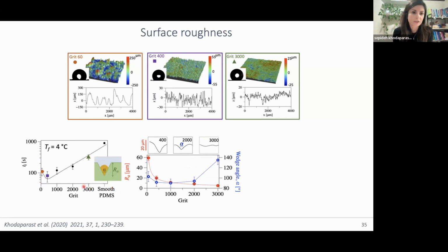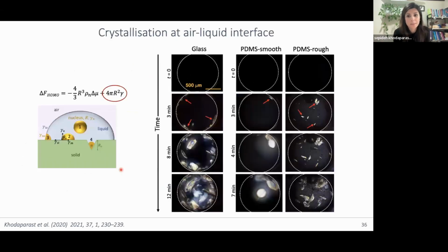you see that there's a minimum value in the curve, and it's not monotonic. It is clearer when you look at both the surface roughness and the wedge angle. The surface roughness goes down with the grit number of the sandpaper, but the wedge angle has this non-monotonic curve. So there is a sweet spot where you have quite small wedge angles, so quite deep, tight wedges, but also small surface roughness, where we have the highest number of chances of nucleation and crystal formation.